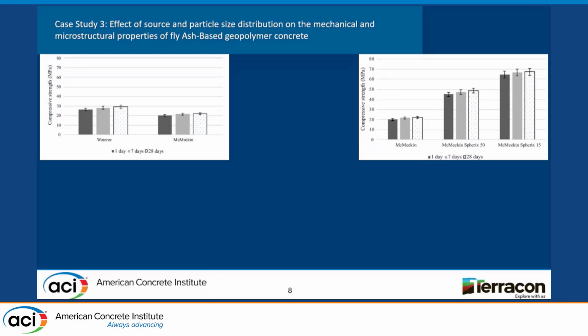And you can see here, once I make the smaller particle size distribution, smaller particle size, the compressive strength is increased from 20 megapascal, which is around 3,000 psi, up to more than 60 megapascal, which is around 9,000 psi, just by using finer particle size distribution. So that's also an advantage for us if we are interested in changing the compressive strength or even durability properties. I tested them. I found it really has a low permeability due to using finer fly ash. And I think you can control it by either changing the source or also by changing the particle size distribution.